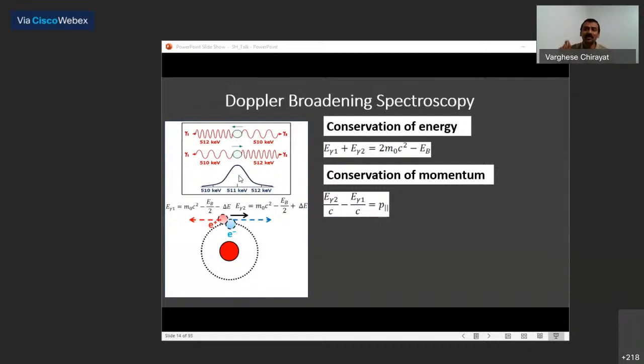Before the positron annihilates, it has almost zero energy. So the momentum of the electron-positron system is dominated by the momentum of the electron with which the positron is annihilating. So this broadening is a direct indication of the momentum of the electron in a direction parallel to the emission of gamma rays. By measuring that broadening, you are basically measuring the momentum of the electron with which the positron annihilated.